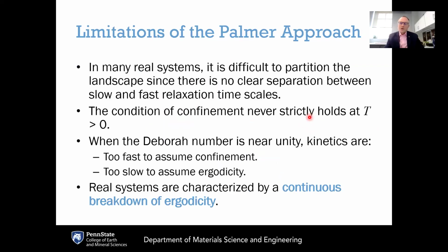Now, Palmer's approach was really foundational for the study of non-ergodic systems. However, there are some limitations to Palmer's approach. In many real systems, it is difficult to partition the energy landscape since there's not necessarily a clear separation between slow and fast relaxation timescales. Another issue is that the condition of confinement never strictly holds for any positive temperature because there's always some probability of making any transition as long as the temperature is above absolute zero and the time scale of observation is longer than zero.